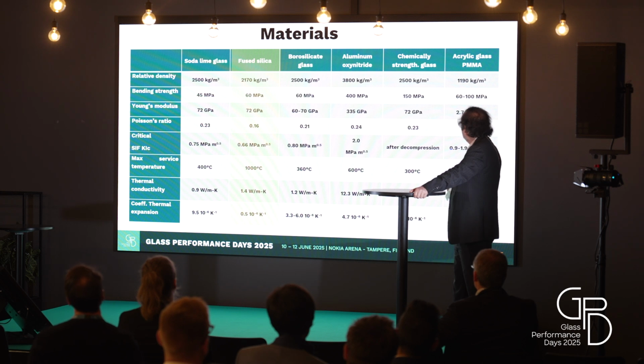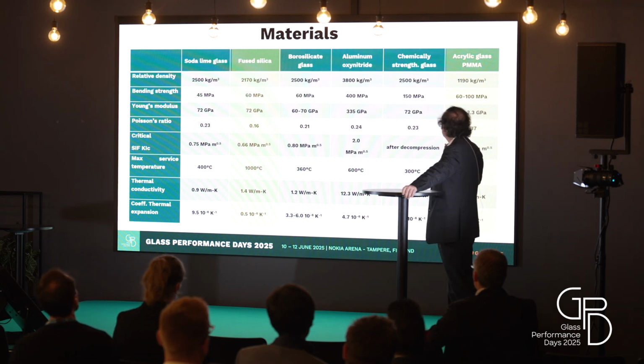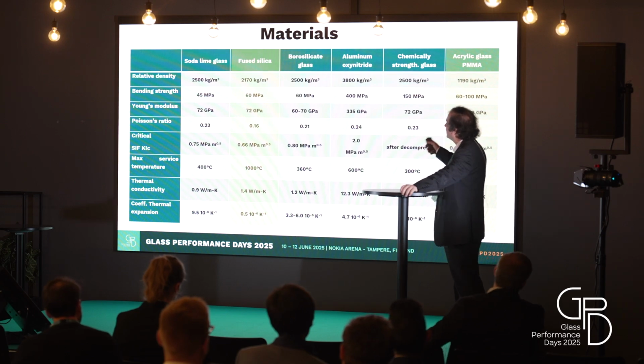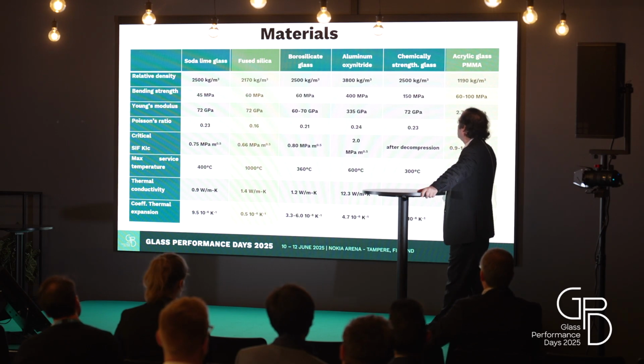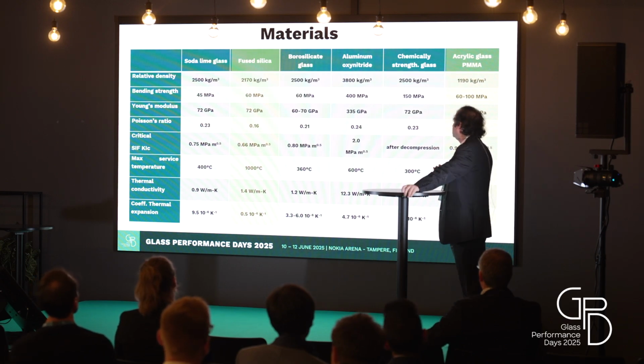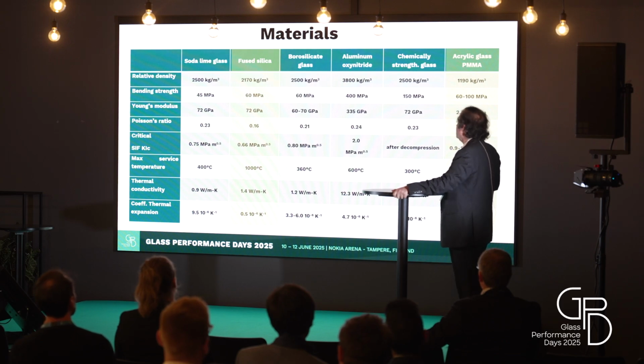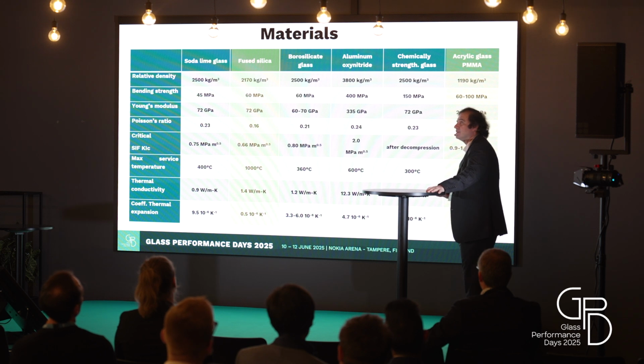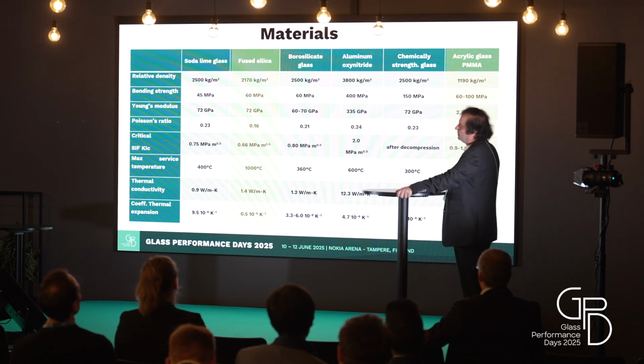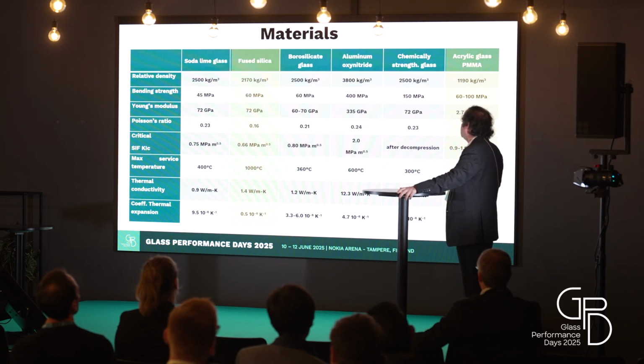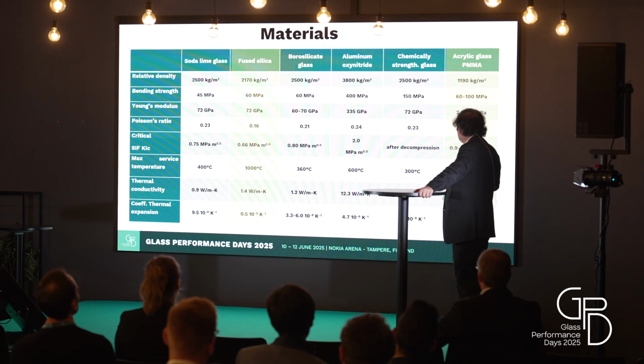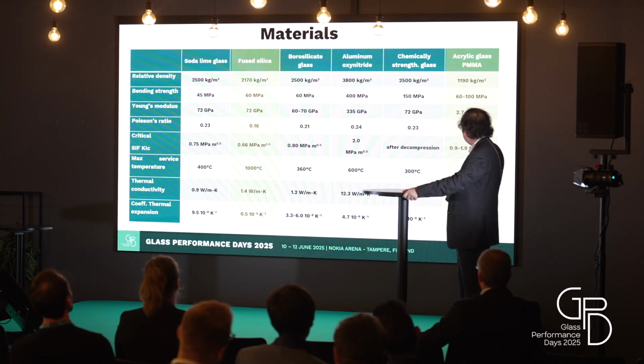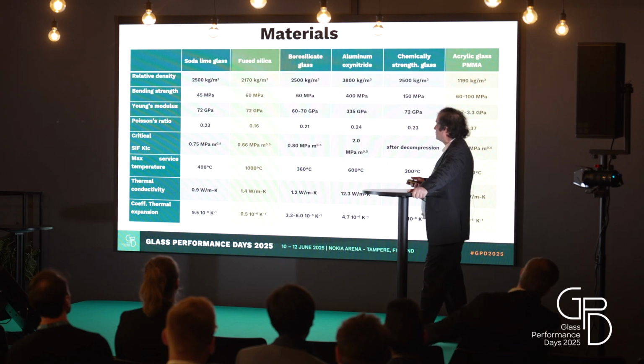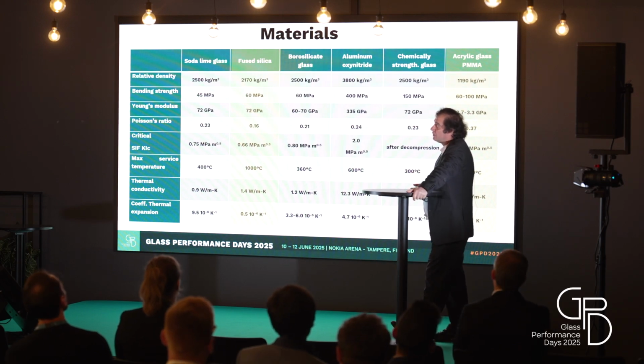These are just a comparison of the various materials. You can see that, yes, acrylic glass has a lower density. I'm just highlighting fused silica and acrylic glass properties. But you can see that whereas the bending strength is comparable, the Young's modulus is much lower. And also the Achilles heel of acrylic glass is the operating temperature, because the glass transition temperature for acrylic glass, which is a PMMA, is about 100 degrees Celsius. And also the coefficient of thermal expansion is quite high compared with that, of course, of fused silica, which has almost a zero coefficient of thermal expansion.